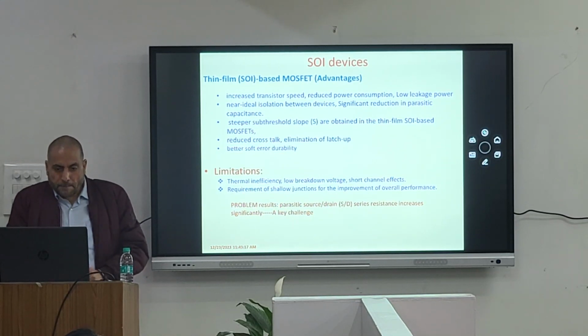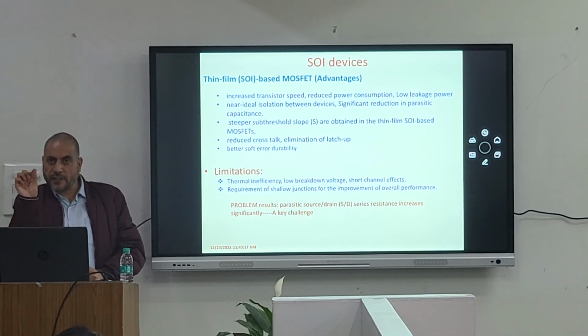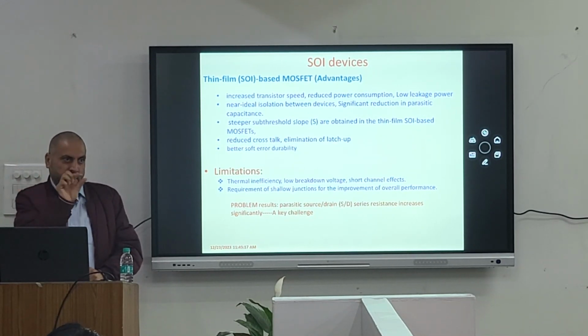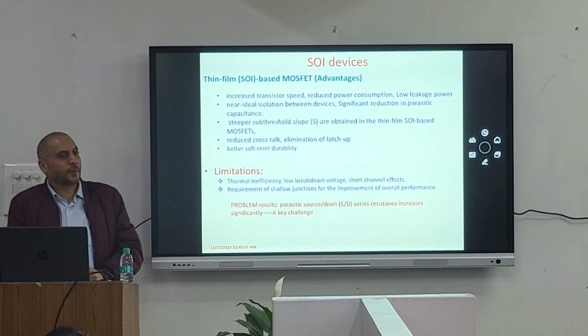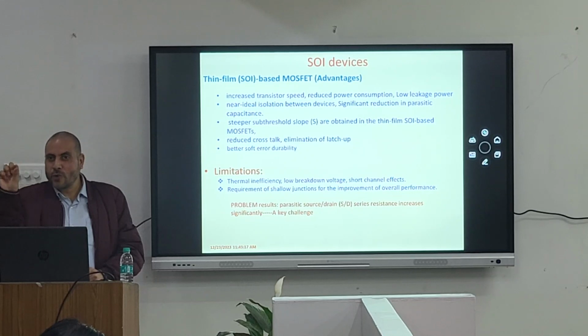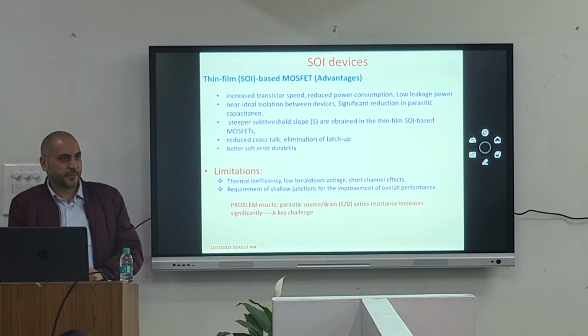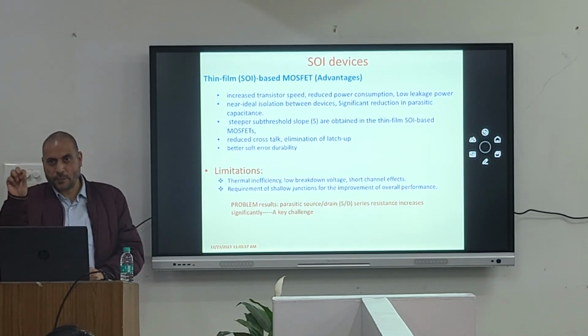Now the thing is that advantages are there for an SOI structure. As I mentioned, thin film SOI has the best SCE suppression. So we have that thin film, and it is giving me the best SCE suppression. But on the flip side, we have an issue. It is thin film, and the source drain series resistance increases significantly. It's a problem. So source drain series resistance is a problem, and at the same time, realizing a thin film is again a problem, right?